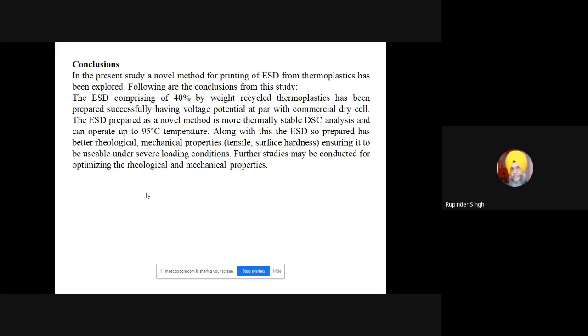But what important we observed out of this is, the cells that we printed, we did the thermal analysis of that particular cell. So what we observed in the thermal analysis, by working up to different temperature range, up to 95 degrees Celsius, this composite is stable, right? Similarly, up to minus 30, this composite was observed as stable. Now this is a great observation, because I can use this type of the cells at extremely high or extremely low temperature. And secondly, I can reuse the 40% of the material